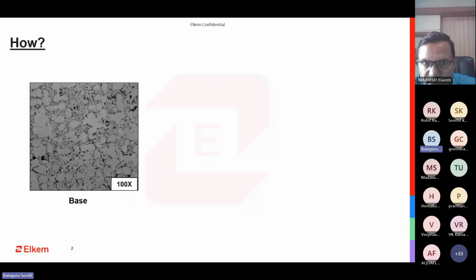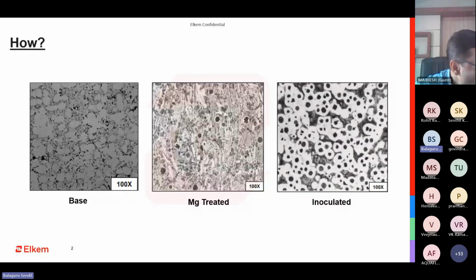The next one is that after magnesium treatment, when you go for an inoculation practice, that is where you see very nice nodules formed. And this is the microstructure that we want, so that we will be able to use it for a lot of engineering applications. Based on how this microstructure changes, we have different mechanical properties. We have various tensile points and various hardness values, which we use for different grades. These different grades are used for different applications, ranging from engineering and automotive all the way to construction, nuclear waste storage, etc. So this is how a typical ductile iron microstructure looks for the base metal after treatment and after finally being inoculated, in your castings.